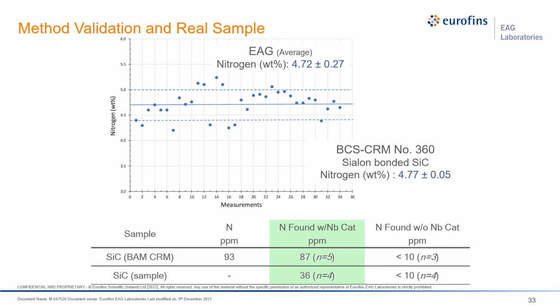In the table, we did another comparison where reference material is compared with an actual silicon carbide sample. Please note that when we attempted to measure the nitrogen without niobium flux, we could not detect nitrogen. Whereas with niobium flux, our results show expected presence of nitrogen for reference material and as well as for the sample.